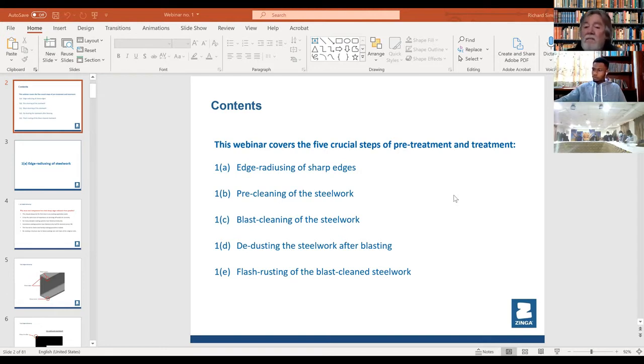So the pre-cleaning is a very, very important step. You don't want to have any contamination being driven into the steelwork while you're blasting. The next phase is blast cleaning. And again, we always go for SA 2.5, which is the standard around the world for most people. But with Zinga, it's the depth, as we always recommend 50 to 70 microns. And I've got another slide, I'll show you why, but it's critical for a lot of blasting work.